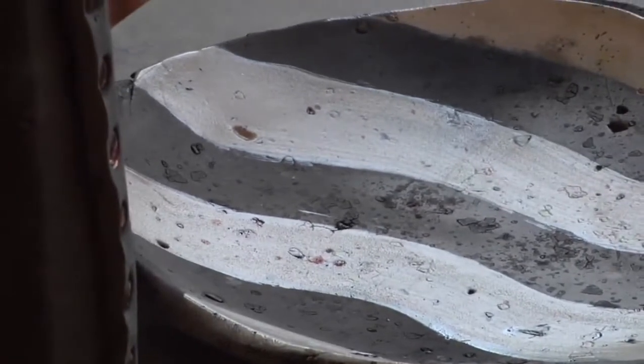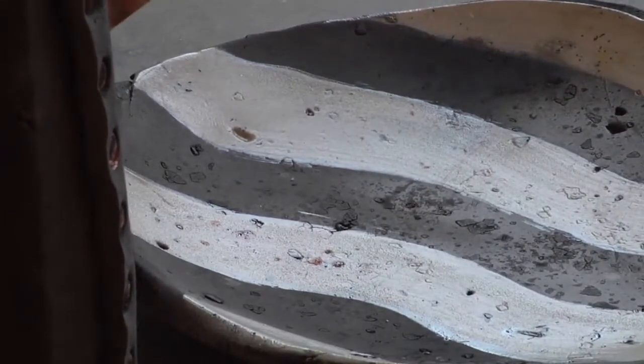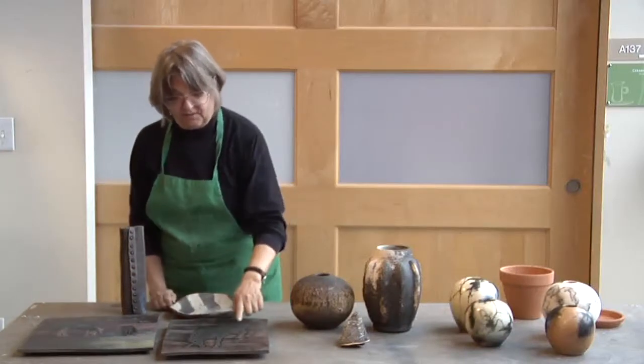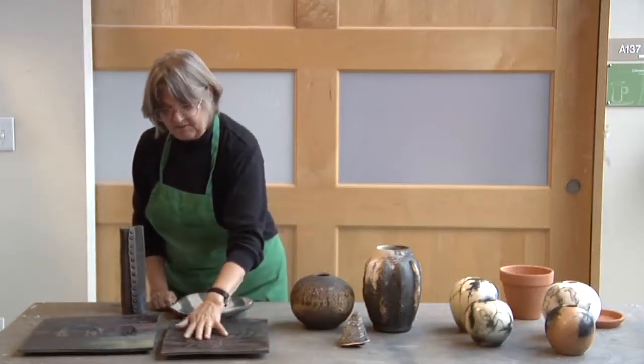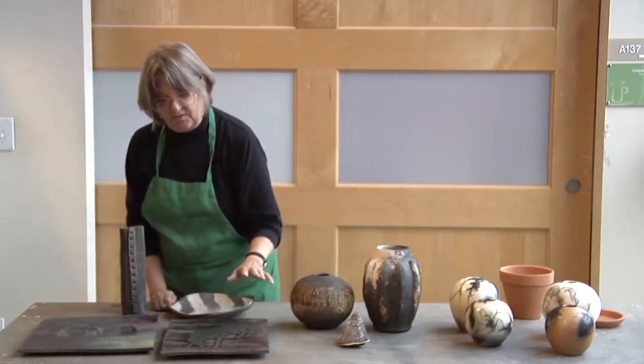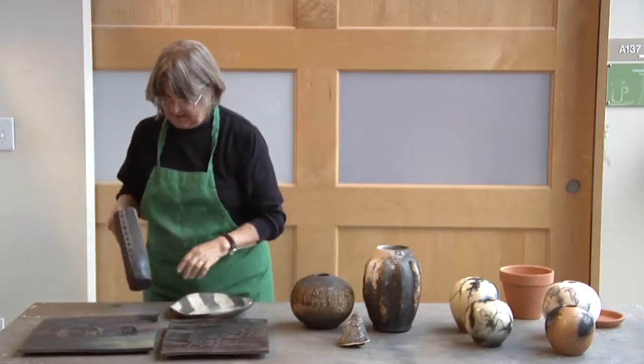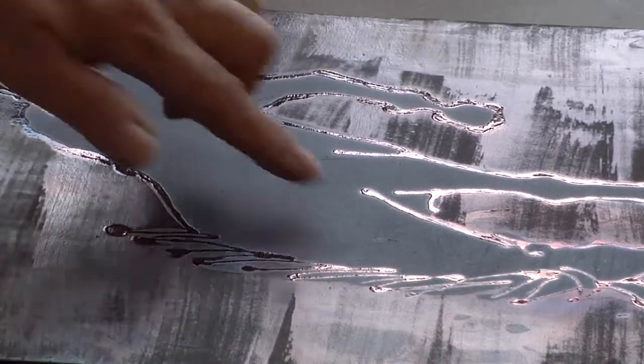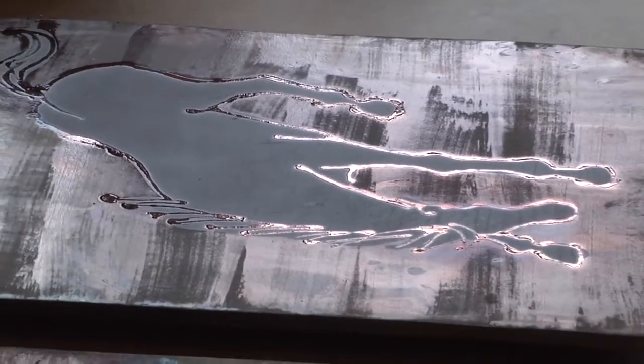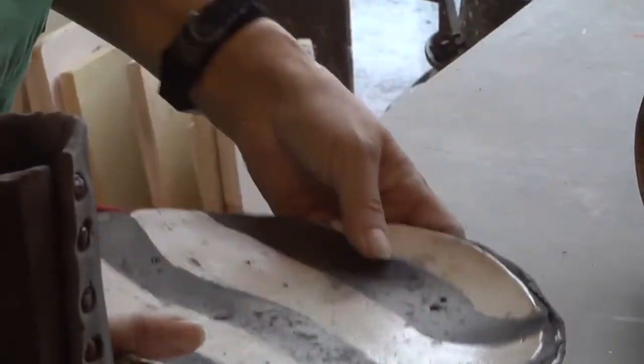These are the only ones that have a glaze on them. And you take them and put them into a combustible chamber like leaves, straw, newspaper. Put a lid on it and let it smoke for about 20 minutes, or half an hour, or till it stops smoking. So the smoke goes into the bare parts of the surface. So the black here is no glaze. And I used a couple different resists here. This was latex resist, this was tape, and this was just not glazing. So you still get the black where you just don't glaze.